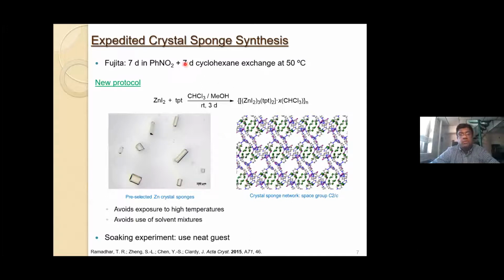And I was able to do that simply by swapping out the nitrobenzene solvent for chloroform. And so what I was able to do was to solubilize TPT in chloroform and layer on top of that a solution of zinc iodide in methanol. And then you let that sit at room temperature for 3 days. And then you're able to get sponges that are viable for the technique. You do get a mixture of different kinds of morphologies. You get sheets, you get twin crystals, and you get these rods or prisms. And these are the kinds of crystals that you want for the technique.